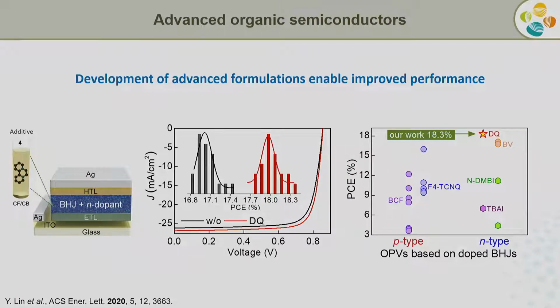So if we take a device which has an efficiency of around 17%, you add this tiny amount of this small molecule, which is essentially an electroactive molecule, acts like a dopant, induces a charge, but also modifies the microstructure of the semiconductor. We can increase this peak performance to over 18%, 1% more. It may not sound exciting, but imagine this 1% extra during the lifetime of that product generating excess power, plus it improves the stability of the device.